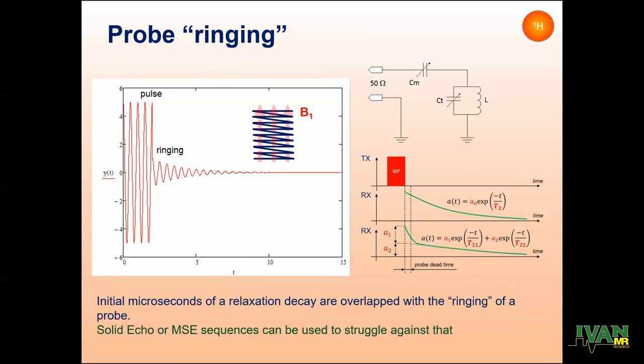And another problem is more serious. This is the so-called ringing time, or dead time of the probe, because you apply a pulse, and after the pulse, the excitation of the NMR is normally some kilovolts on the coil, and the reply of the spin system induces, I guess, some microvolts in the coil. And this is a huge gap, and the transition takes some time. Normally it's around 10 microseconds, somehow longer, somehow shorter, but looking at the picture, these 10 microseconds are serious. A considerable part of the FID signal is hidden behind the transition process. That's why this is a great problem, and there are some hardware tricks to overcome that.